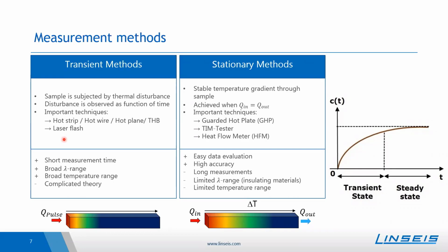But the problem with the transient methods is that the theory is typically more complex, so that the evaluation is a little bit more complex. And for the laser flash, only the thermal diffusivity is determined and not directly the thermal conductivity. But this is a disadvantage of the laser flash and not of the transient method in general.